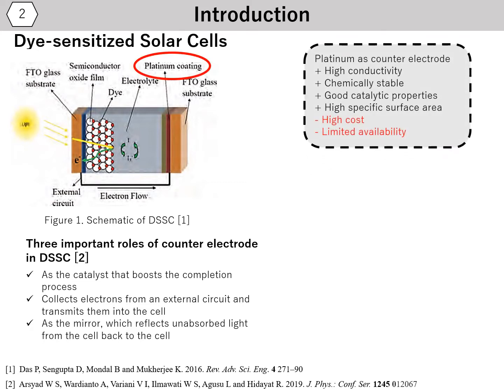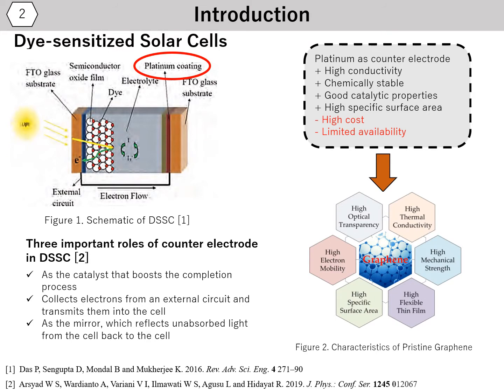Platinum is commonly used as counter electrode, has some advantages like high conductivity, chemically stable, and so on, but it has high cost and limited availability. So we have to find an alternative for platinum replacement material. One alternative material for counter electrode is graphene. Pristine graphene is one of carbon electrode that has some outstanding characteristics like high electron mobility and high surface area.